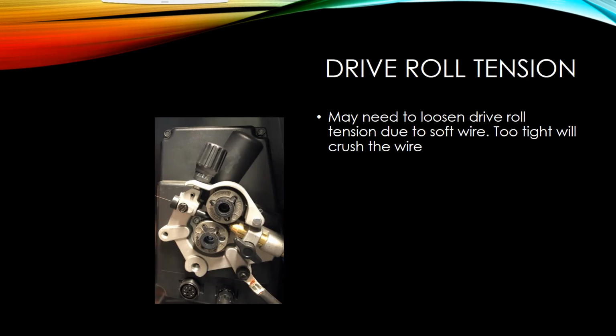Another common issue that I see out there is just ensuring that you have the right drive roll set up. On this one, I have a .023 V groove in there just to show you that it is incorrect. You would want to use a U groove for aluminum. But also, this tension here is crucial. If you have that tightened way too tight, it's going to put a lot of pressure on your drive rolls, which will put a lot of pressure on your wire and could crush the wire. So something to pay attention to there. You might want to loosen up that tension just a little bit for aluminum.